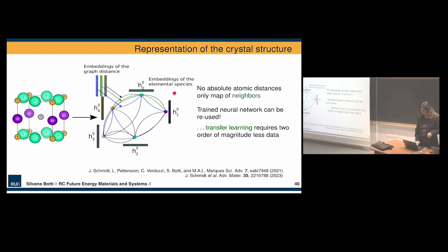So we use the crystal graph to represent a crystalline compound. So this was already published some years before this. But what we did was not to use information on the lattice parameters. So we were introducing a certain prototype, so it's a certain defined symmetry and coordination for our crystal structure, but we were not necessarily knowing what the lattice constants were, because otherwise we would have to relax the structure with, for example, machine learning force fields or DFT to get the crystal structure. We didn't want to do that.